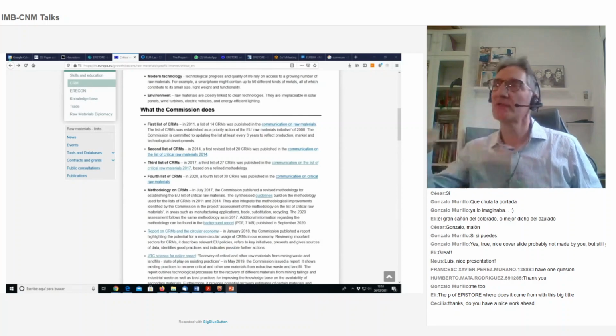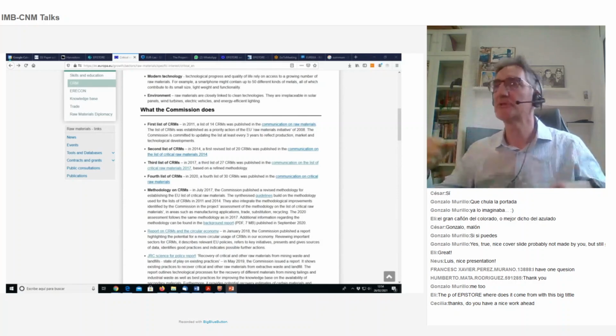But in order to try to avoid this, this area will be crisscrossed with those regions that I mentioned that were highly doped, and those will act as a kind of tensors in order to keep the membranes relatively flat. So we have a strategy for that, but you're right, and stress could play an important role here. Okay, thank you.